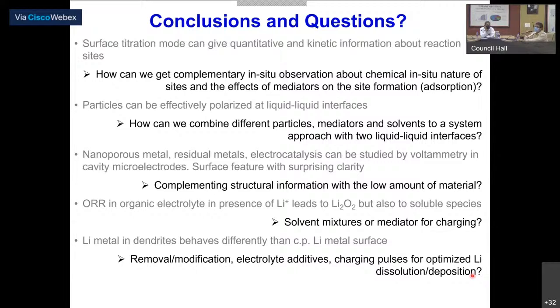Probably meanwhile, Professor, can I just ask something? Yes, please go ahead. Definitely the entire talk was very interesting, but this liquid-liquid interface, what is the typical dimension of your electrodes there when you use them? The pipettes can be drawn out to very small dimensions. I think probably our ones are in the range of 10 to 20 micrometers, 5 micrometers, and the microelectrode is typically 25 if there's not another special requirement. That is to stabilize this interface mechanically and to also record a defined electrochemistry at their surface.